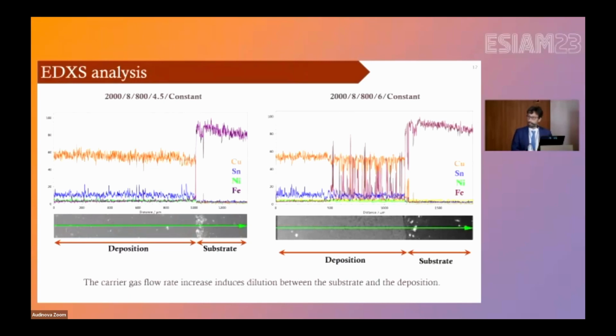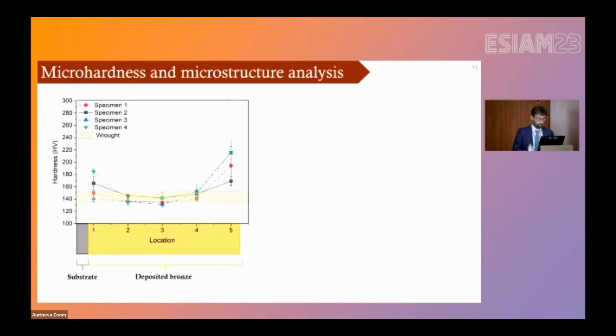Then we try to analyze the chemical composition gradient across the interface in 2 scenarios. In one we have no dilution because the gas flow rate was low, and in the second case, on the right, the gas flow rate was enough to impart dilution. So the chemical composition you see here shows a gradual transition in the bronze content, in contrast to the case on the left in which we have a sudden and sharp transition in the chemical composition.